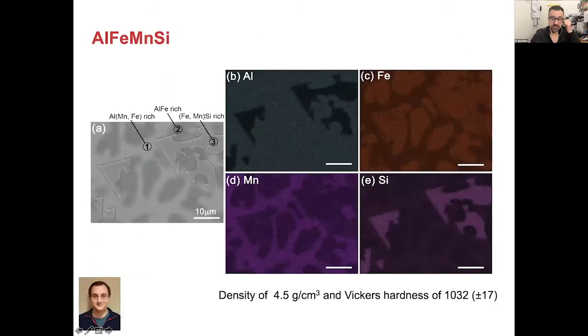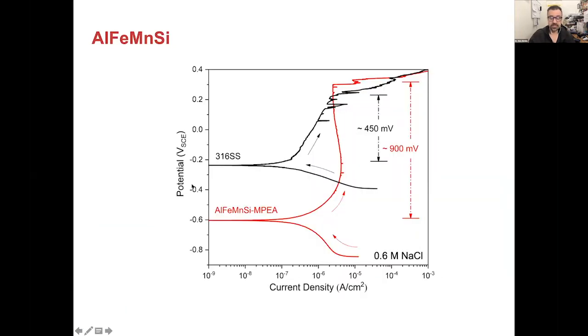Well, it turns out that Sean O'Brien, the PhD student, made this particular alloy. He's made similar alloys many times by arc melting, and you get a significantly lower density than steel and a tremendously high Vickers hardness in a multi-phase alloy, and you get a tremendous window of passivity. Quite remarkable. Actually, this even had me floored.